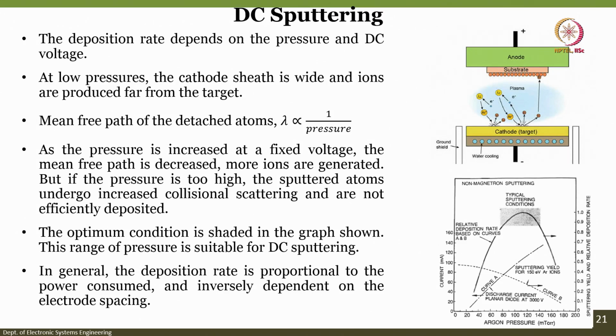The first one is DC sputtering, and the deposition rate depends on the pressure and DC voltage. We can see here there is a cathode, there is an anode, you apply a DC between the two, and then there is a ground shield, there is a water cooling mechanism. So, the target gets cooled down, and when there is bombardment of the ions onto this target, the atoms get dislodged and start depositing on the substrate.